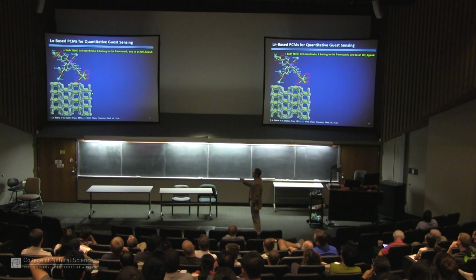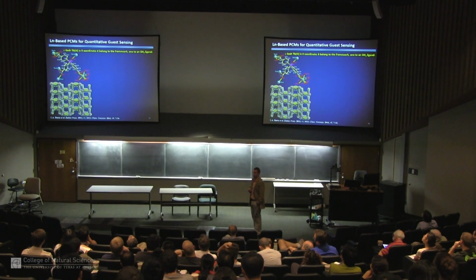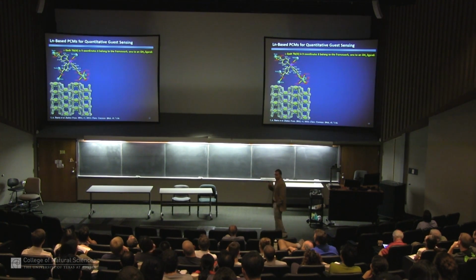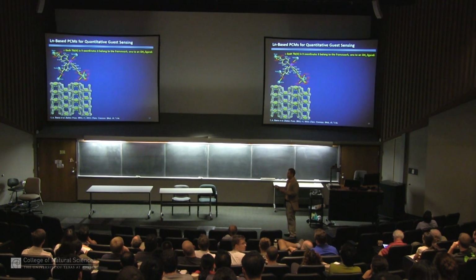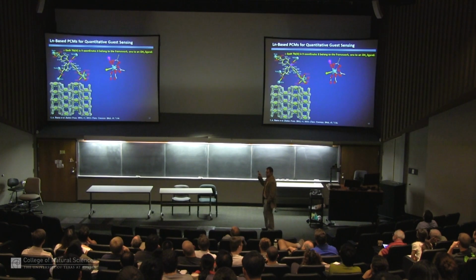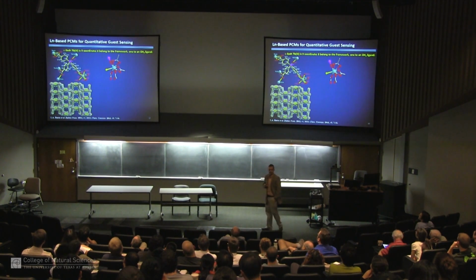We make a very rigid and highly porous framework. And this is where crystallography, again, is very important. You couldn't get this from an amorphous material. We know that every single metal site that forms the polymer has these 8 groups attached to it, but one of them is a water ligand. And you might think that's surprising that water's in there. We actually make the material in water, so there's water and a couple of other solvents.